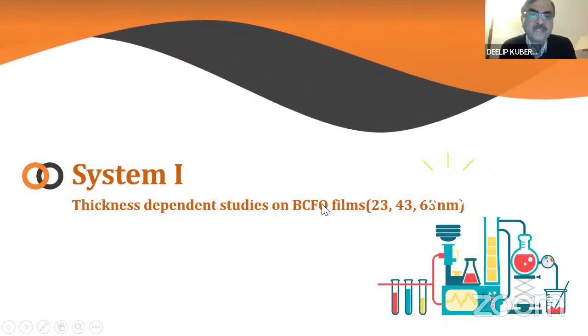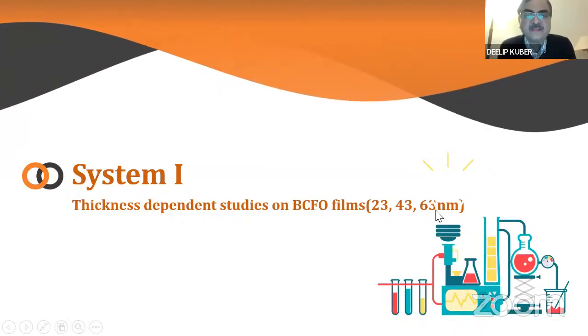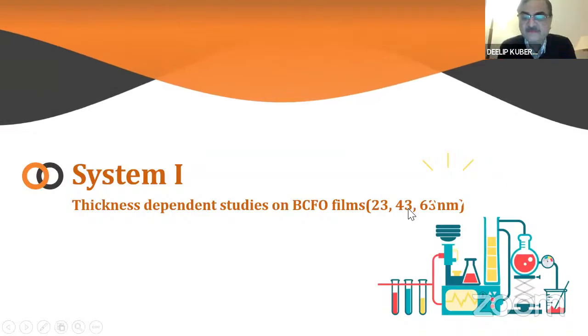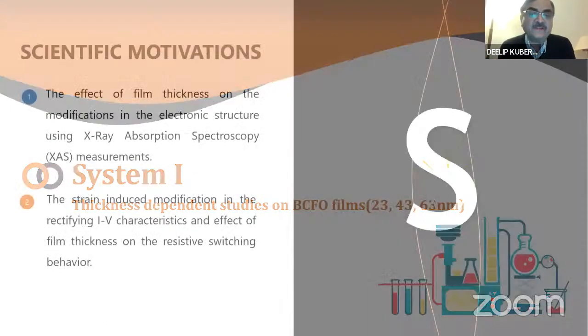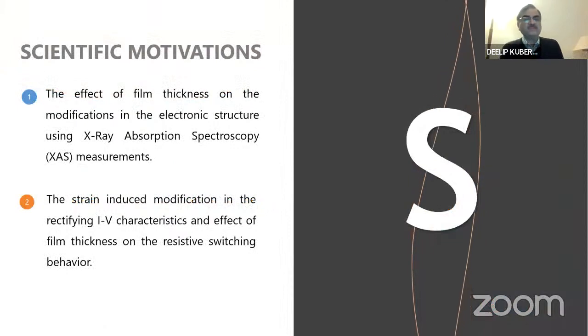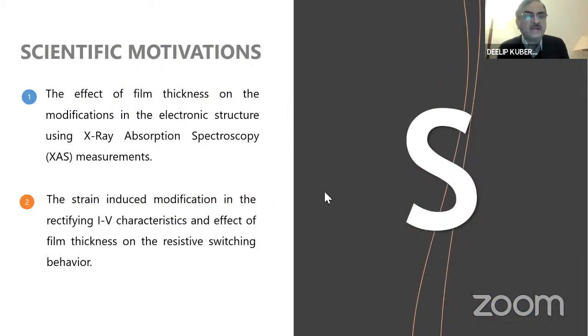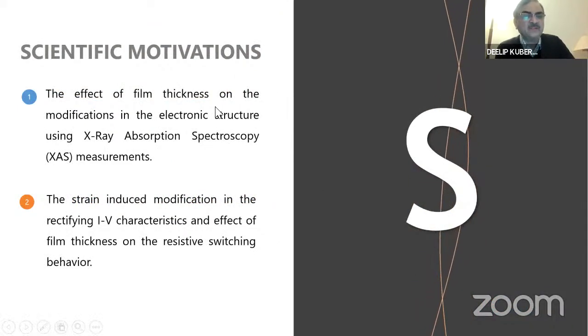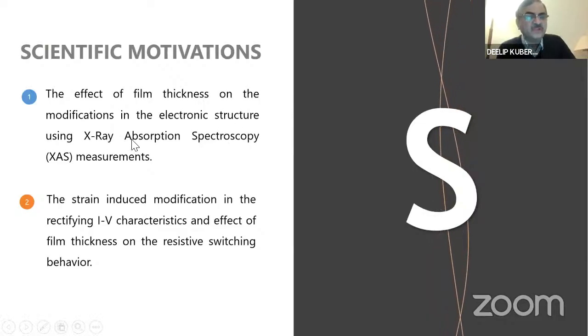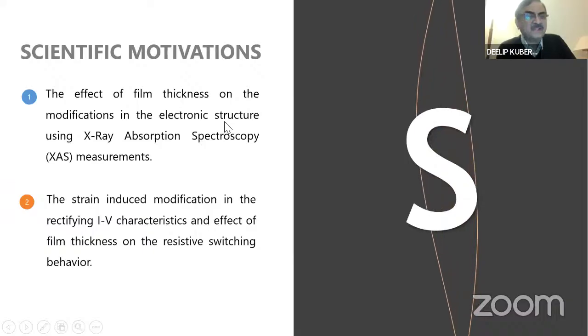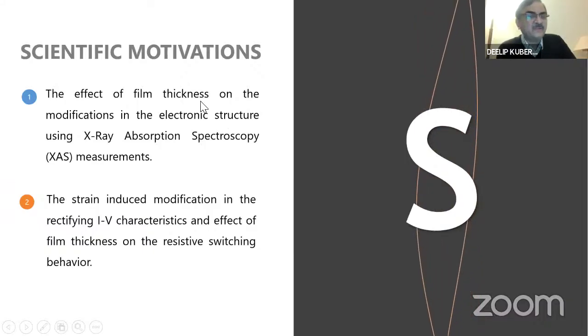So, thickness dependent studies on the calcium doped BiFeO3. I have selected 3 thicknesses, 23 nanometers, 43 and 63, and these thicknesses were tried 2 or 3 times and confirmed by different characterization techniques. So what was the motivation for undertaking this work? I wanted to see the effect of film thickness on the modifications in the electronic structure using X-ray absorption spectroscopy measurements, and how the electronic structure gets modified as a function of the film thickness.